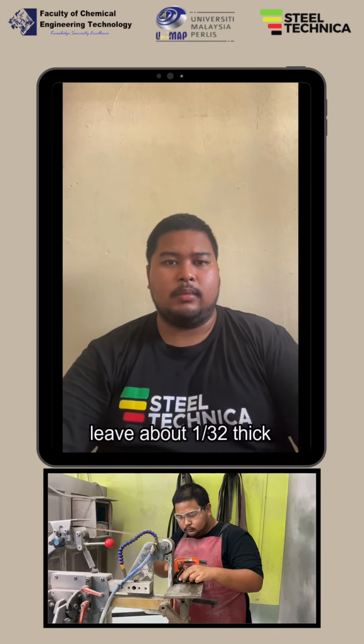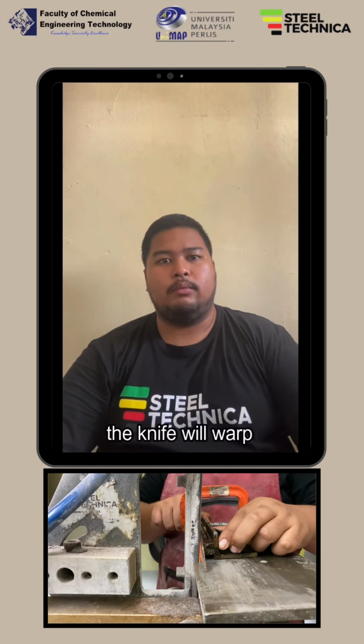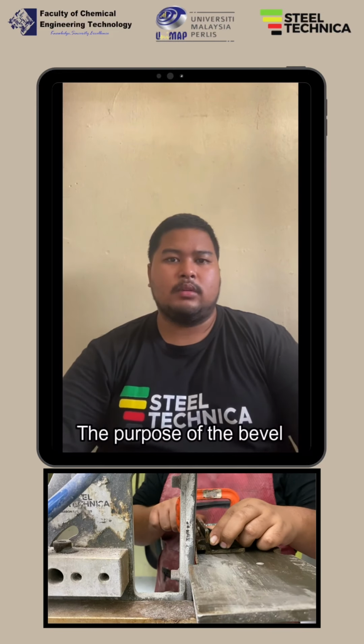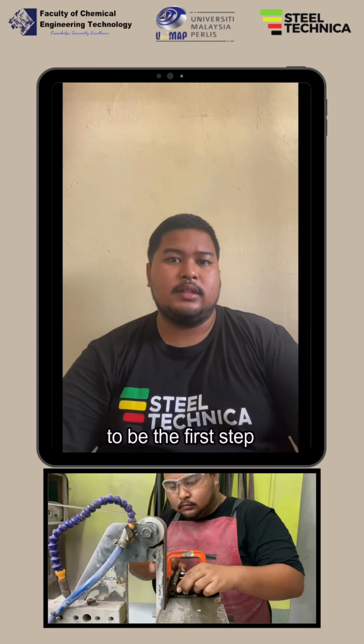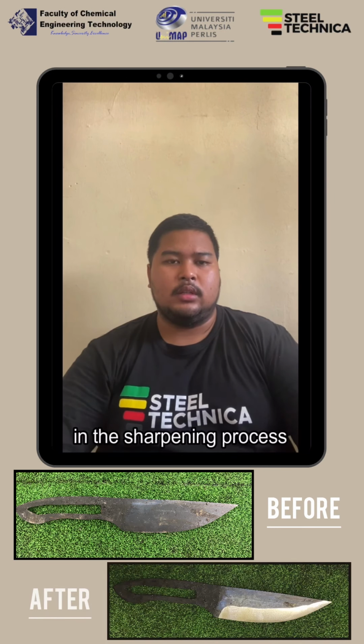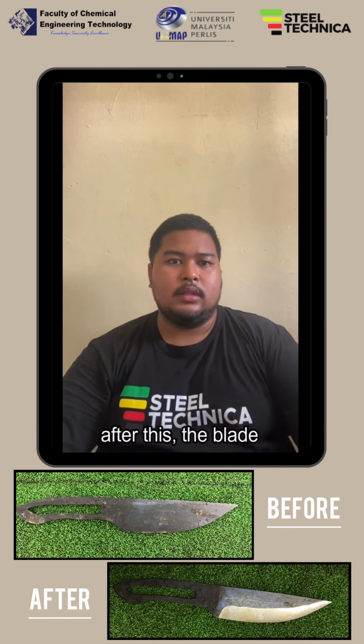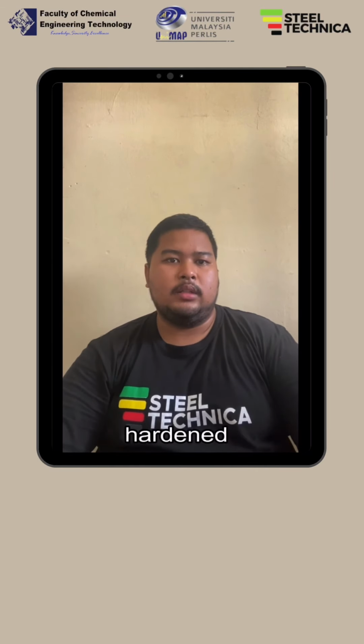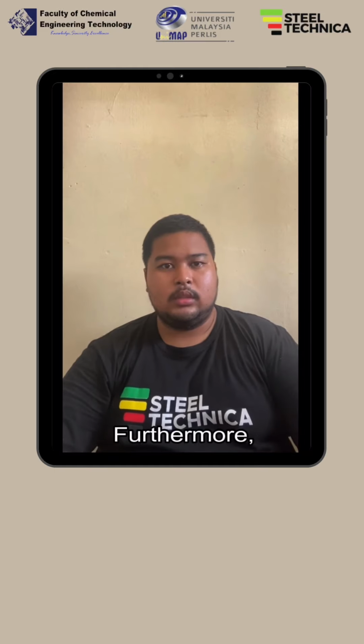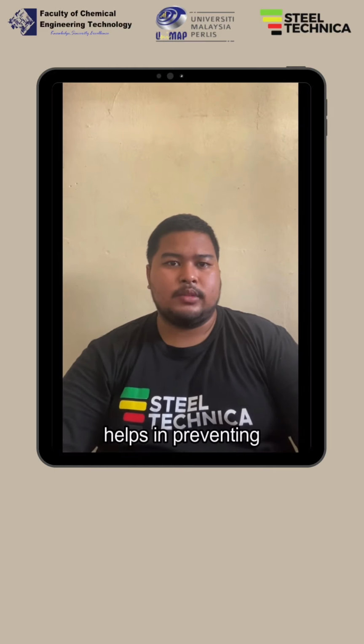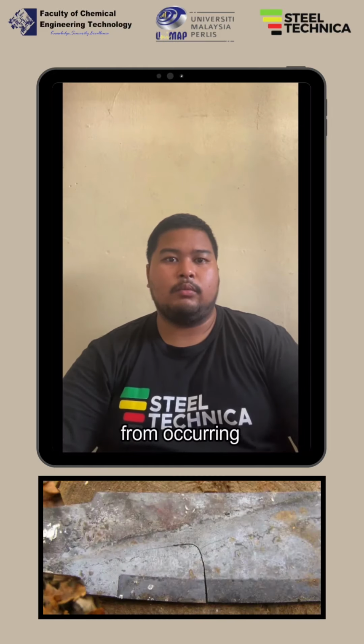When doing the knife bevel, the blade edge will be left about 1/32 thick, because if not, the knife will warp during the heat treat. The purpose of the bevel on the blade is to be the first step in the sharpening process. This is because after this, the blade will go through a heat treatment process and the blade will become hardened and harder to shape. Furthermore, the bevel on the blade helps in preventing stress cracking from occurring during the heat treatment process.